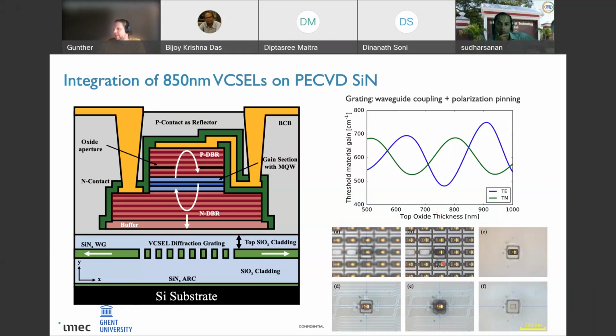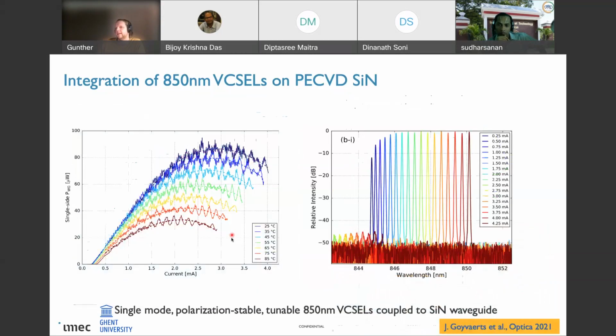So here you see the VCSELs on the III-V source wafer. So again, a very dense array. In this case, we picked up individual VCSELs and printed them on the silicon nitride grating coupler here, resulting in low threshold lasers, sub half a milliamp, single polarization, and single wavelength emission devices here.